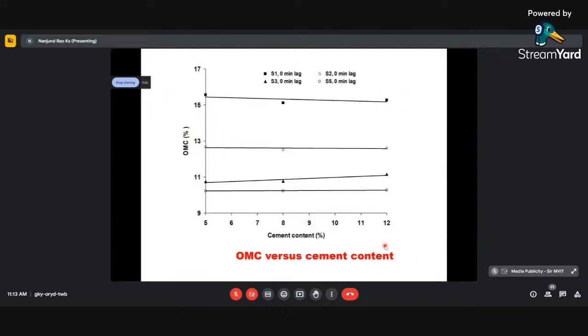Now, coming to the optimum moisture content, we say we are stabilizing it, and we looked at four soils, S1, S2, S3, S5. 0-minute lag means the moment we add water, we immediately get the specimens and the optimum moisture content at different times. So what this figure is showing you is, by the addition of cement, anywhere from 5 to 12%, the optimum moisture content is not getting altered. Whereas it all depends upon the soil type. For example, the soil designated S1 requires a higher amount of water for OMC for the same cement content.